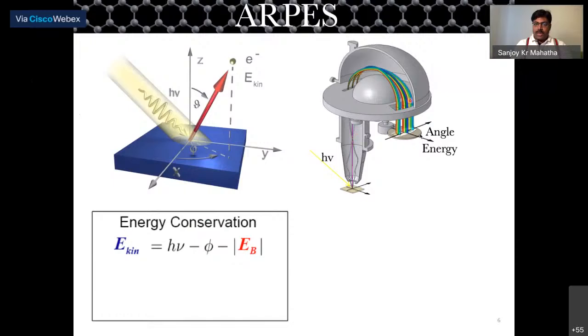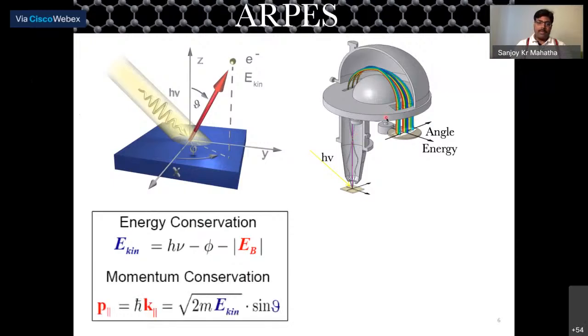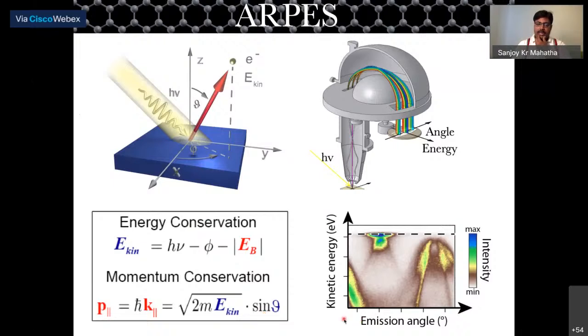And using this kind of state-of-the-art detector, one can also map the emission angle of the electrons with respect to the surface normal. Here you can see in this detector, the electrons emitted with different emission angles are mapped onto different parts of the detector. In this way, the emission angle theta can be converted into K parallel, which is basically the momentum, the wave vector of the electron. So in a single shot, what we get is basically kinetic energy versus emission angle. And then, as I said, by using this equation, the whole spectrum or whole image can be converted into binding energy versus K parallel. And this is nothing but the band structure of that solid surface, which is energy versus momentum.